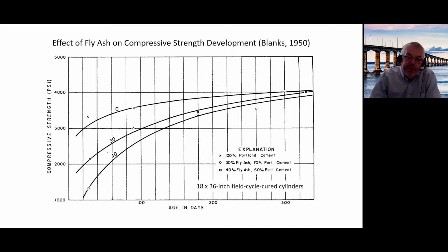Blanks published some information on this, showing the strength development, typical curves that you'll see in the literature throughout the years, showing that fly ash has a reduced strength at early age, but by the time you get out to about a year, even at 40% replacement, strength is equivalent to cement concrete.